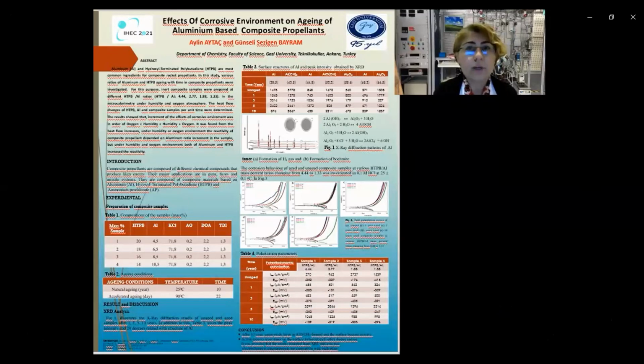When the samples after 5 years and 10 years are compared with each other, the current density decreases again. It is obvious that current density has a tendency to change with the aging time, but there is not any relationship between corrosion potential and the other variables. So based on the TFL extrapolation curves and the microstructural analysis, we can say there was a aluminum oxide layer